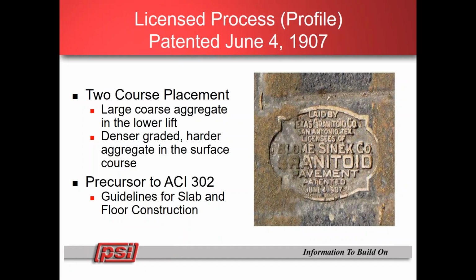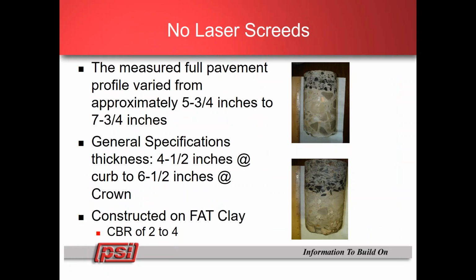This is the licensed process that we're talking about. It was patented on June 4th, 1907 by Blome-Sinek Company, Granitoid. The contract for Belknap Place was contracted to Granitoid of Texas. This patented process uses a two-course concrete placement, a large coarse aggregate in the lower lift and a denser graded concrete aggregate in the surface. It's somewhat of a precursor to ACI 302, which offers the guidelines for a shake finish for slabs and floor construction that are for heavy industrial use. There were no laser screeds in the time.